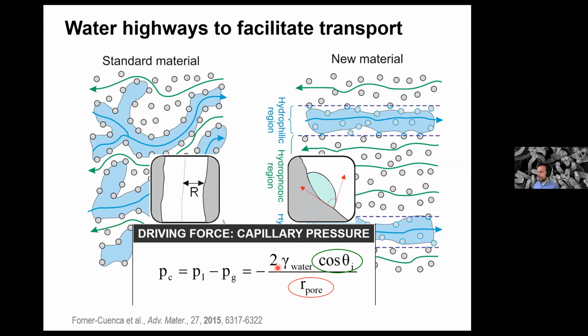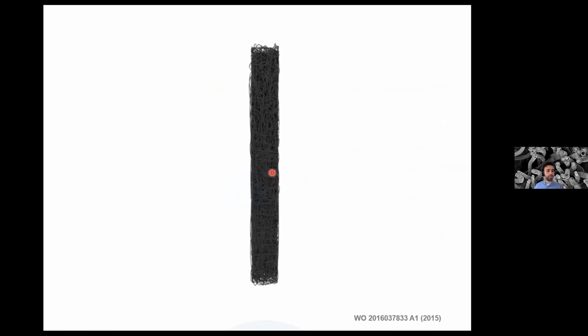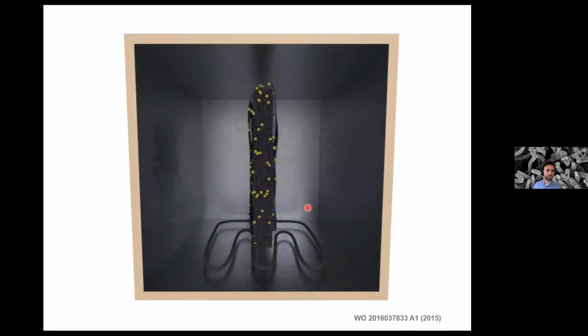All right, so we were determined to essentially modify the contact angle, and how do we do that? So we begin with a carbon fiber substrate that is a conductive scaffold. I'm sure that you're familiar with these carbon fiber substrates. And first, we coat it with a hydrophobic polymer like Teflon. And you expose that to a thermal treatment so that you can evaporate the solvent and sinter the polymer. Now, this is traditional state-of-the-art hydrophobic GDEs.